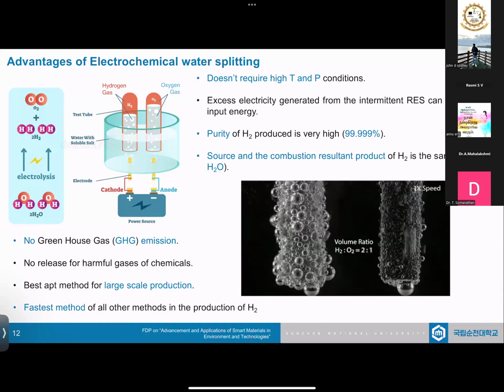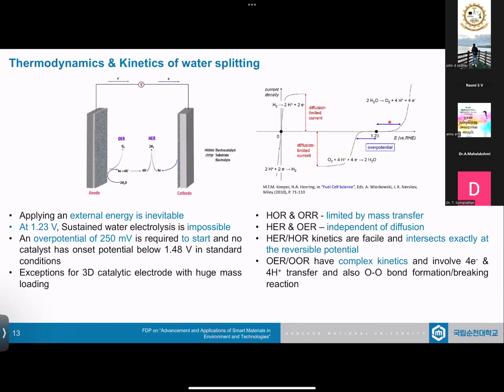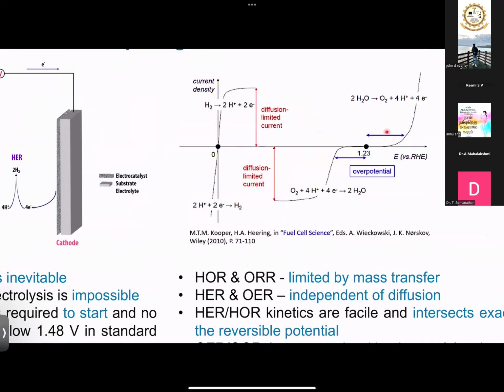You get 99.99% pure hydrogen, because in extensive production you sometimes have some oxygen crossover happening in the membranes, and that might slightly contaminate the produced hydrogen, but it's not extensive, and it can easily be removed, and you can get much purer hydrogen. And as I said, when you break water, you get hydrogen, and when you burn hydrogen, you get water again, which makes it cleaner. So let's look into what happens inside, and we'll go into a more in-depth discussion.